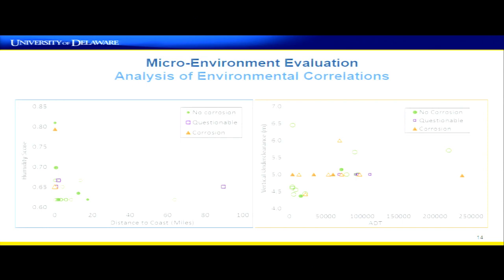Humidity is not necessarily as clear, though. We see bridges that are in more humid locations that were fine. So what this is showing is that it's not just these two variables. There's a third variable, which is chloride concentration, that explains this difference. If you could easily see a 3D graph of this and have chloride on a third axis, these orange data points where there's corrosion are in a different three-dimensional space with higher chloride concentrations than the other bridges that do not have corrosion. So it's a combination of distance to the coast, humidity, and chloride that we've quantified.